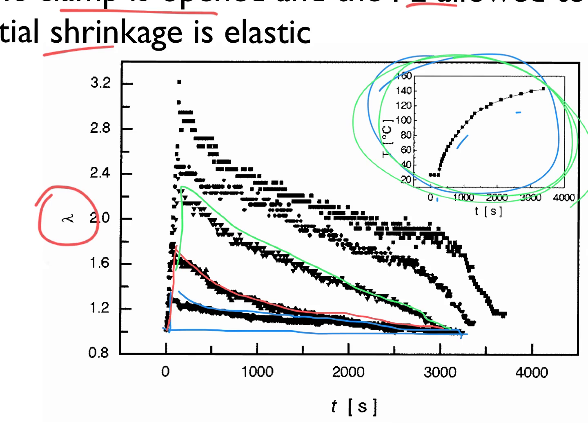But even under those pretty generous conditions, if you go to a high enough value of lambda, 3.2, so it's 300% its original length, we end up with something that is non-recoverable. All right, and so there's that plastic strain, even if you give it all kinds of energy to let entropy drive it back to its original dimensions. At some point, this is not able to restore those initial dimensions, because matter has just moved around too much for entropy to bring it back to the original shape. So that's like when you get to what's called plastic deformation, or you have permanent plastic deformation.